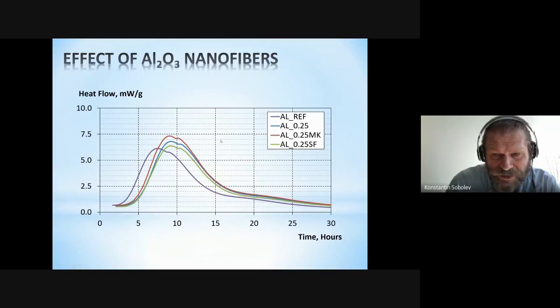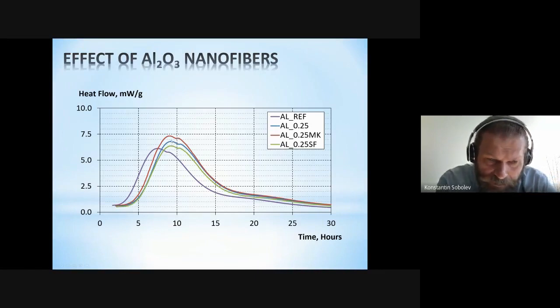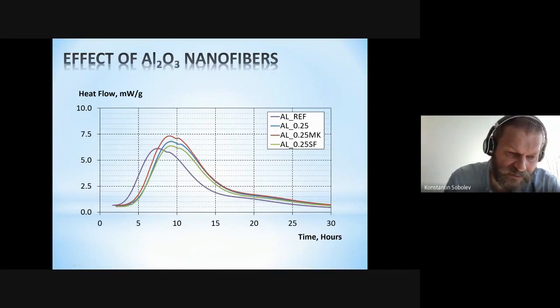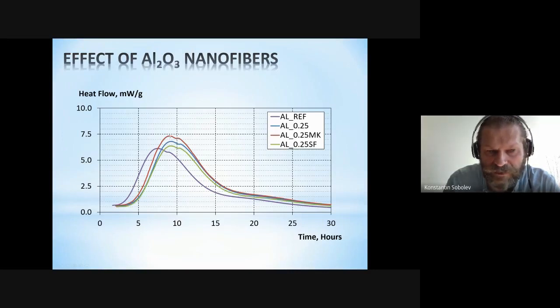Because of the dispersion, we can really achieve a good dispersion of these products. They are easily dispersible. And when we incorporate them into Portland cement systems, we realize we can have considerable enhancement of heat of hydration. And we still observe some delays of heat of hydration. This is related to the processing technology, because when we use dispersion of nanofibers, some of the superplasticizer is damaged due to ultrasonification, and it is causing the delay in hydration. But you can see that heat flow, really peak heat flows, are improved.